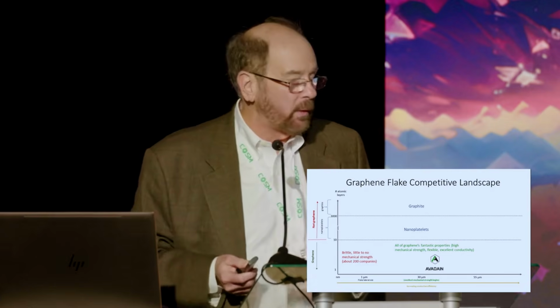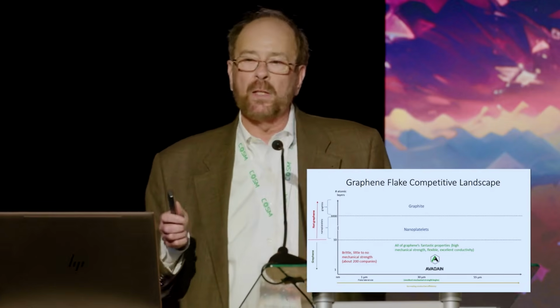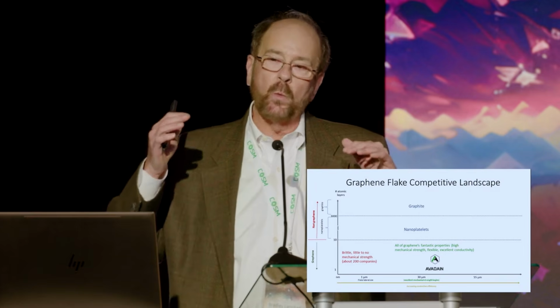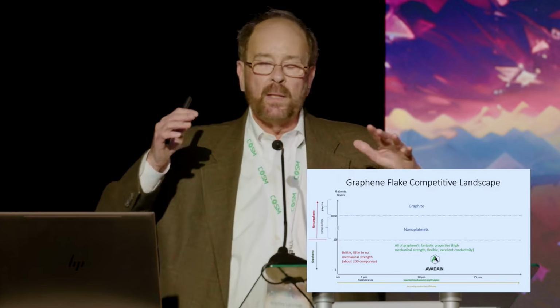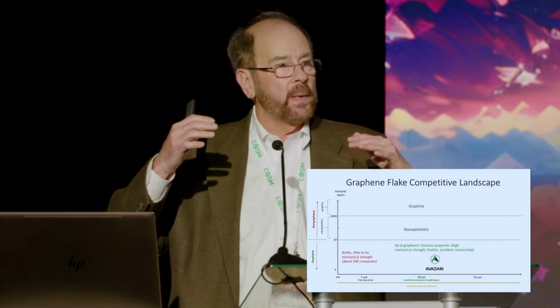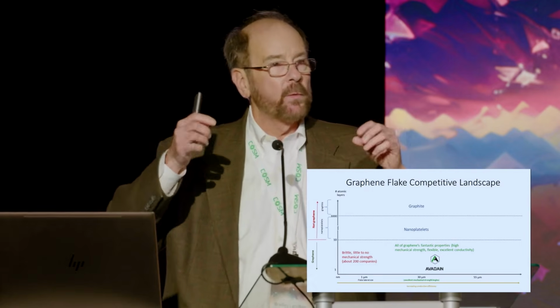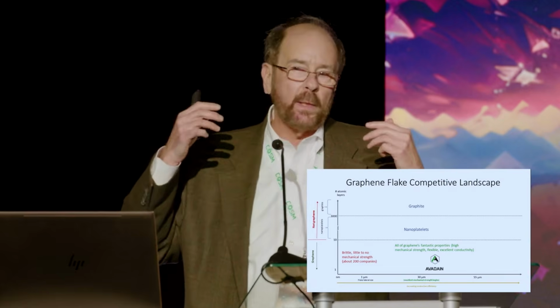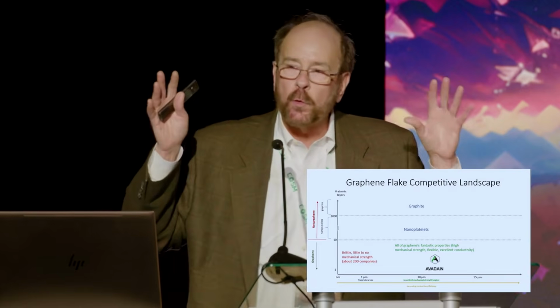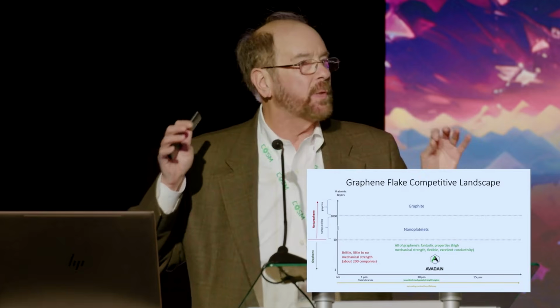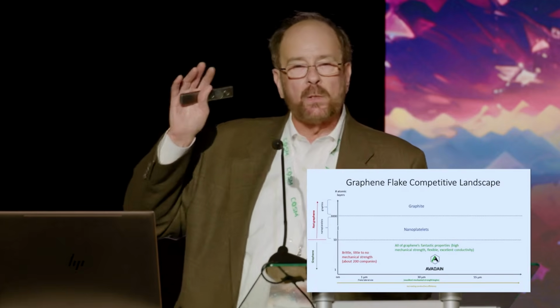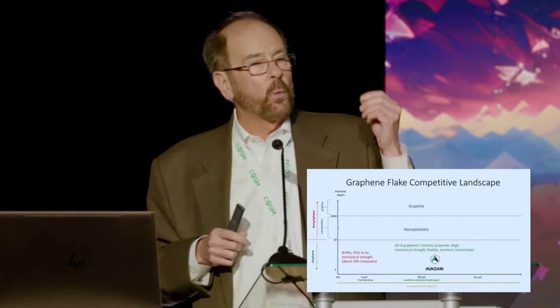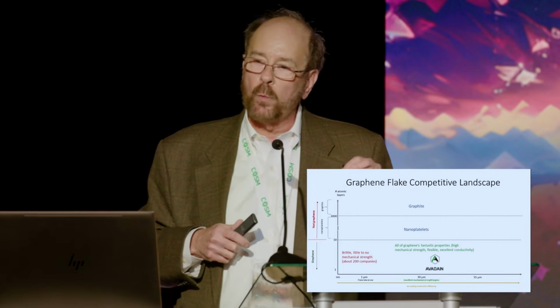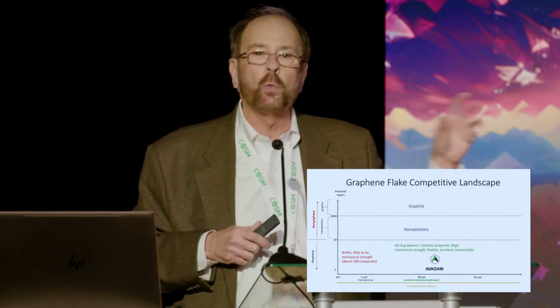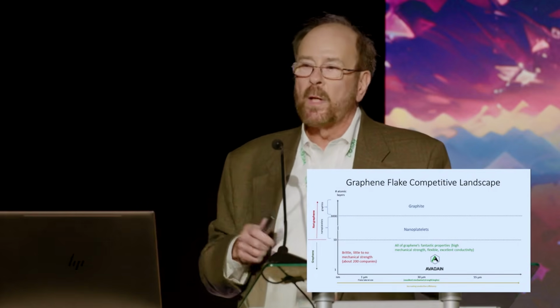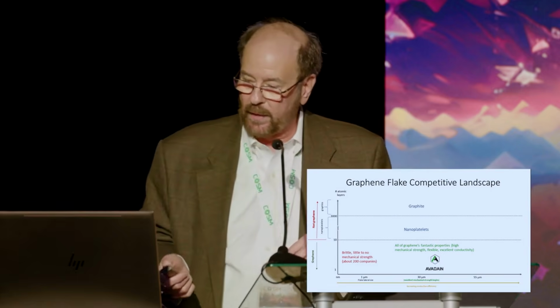We use a method called electrochemical exfoliation, and that is to take the graphite, put it through an electrochemical process, and inject hydrogen between the layers of graphite to create these large flakes. Now, we don't actually make large flakes. What we do is we preserve the large flake size that exists in the graphite. And that's the difference between the top-down and the bottoms-up method. When we work from the bottom up, we're really dealing in nanometer scale graphene, so basically 2 orders of magnitude smaller than what is naturally occurring in graphite.